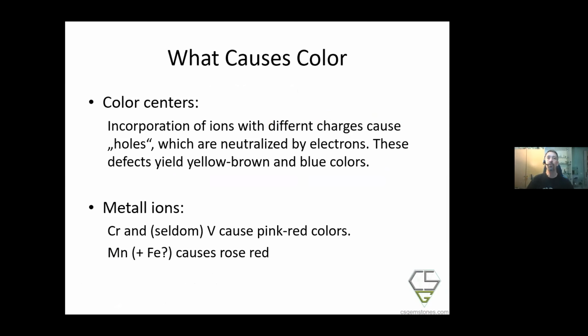Now, what causes these colors? I already told you in the beginning, the majority is the color centers. Color centers is more or less the incorporation of ions with different charges that cause holes. So you might remember from your basic chemistry classes, even in high school, everything needs to be neutral in order to be balanced. So if we incorporate an ion that has a higher oxidation state, like the one that should be sitting on this place, we need to make up this charge difference. And this can, for example, be done by oxygen or by single trapped electrons. And very often we have these trapped electrons, and these defects cause the yellowish to brown and the blue colors.